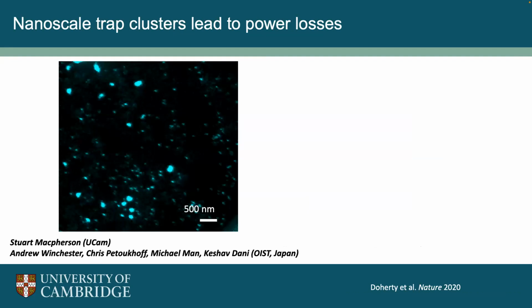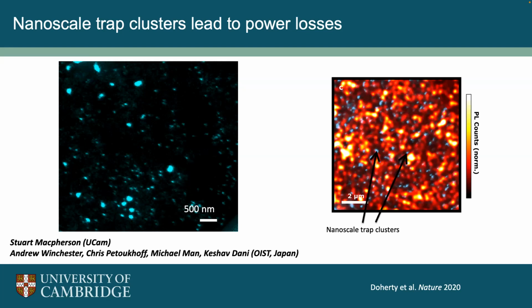What we've seen is also that those luminescence maps I showed, what we find is actually there are really small defect clusters that are scattered around the films. So they're really tiny, about tens of nanometers in size. They're not entire grains that are full of defects. They're just small clusters that are spotted around the film. And what we see is actually these little clusters directly relate to where we have luminescence losses. So this is a map. The color map is showing the photoluminescence. Remember, the light coming out. And what we see is where we see the dark regions, so the black regions, we see these defect clusters appearing. So these defect clusters are problematic for these power losses.